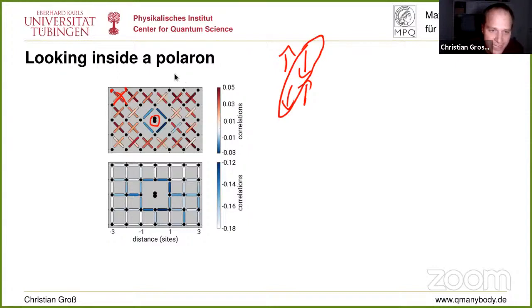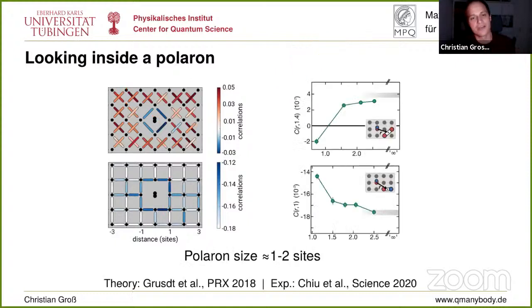And this change of correlations is also true if we look at this next nearest neighbor correlator here, and you see this enhancement of negative correlations around that doublon in this square here. Now we can of course make this more quantitative and try to find a measure for the radius of that polaron. So how big is this guy, right? And for that, we azimuthally average those correlations to get better signal to noise. And what we get then is shown here with the first thing to look at.